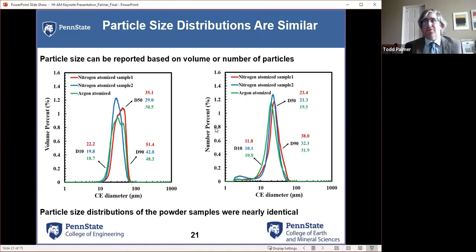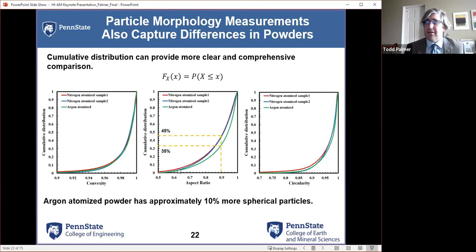Now, if we look at these three powder lots from a particle size distribution standpoint, we're not seeing any real difference. We're seeing basically similar volume percents and similar number percents, a couple different ways. Volume percent is, for each of these diameters, the volume of the powder that's measured. Looking at things on a number density distribution will usually amplify the presence of fines, and we see some of that here.